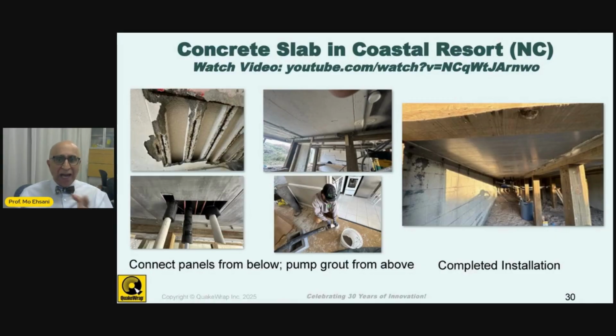So when you pump the grout with your grout pump, it would flow over these. But it would take a little bit away from the flow capacity of this, but I don't think, like in this case in Phoenix, that would have been a major problem. But the repair would be much faster, of course, and then you get a lot of strength out of this system. Obviously, for the one project in Phoenix, as I told you, for that culvert, we didn't have this SPiRe Plus available then, but we have used it on other slab projects.